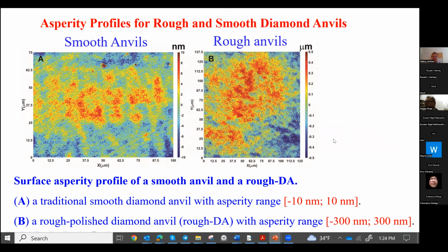The usual assumption was that friction stress reaches yield strength in shear, and this was used to determine pressure dependence of yield strength in shear. What we found is that friction stress with traditional anvils hardly reaches half of yield strength in shear, and this shows an error in previous work which determined yield strength in shear.